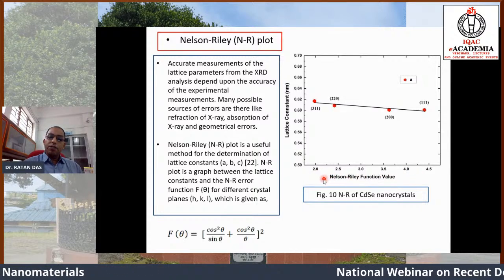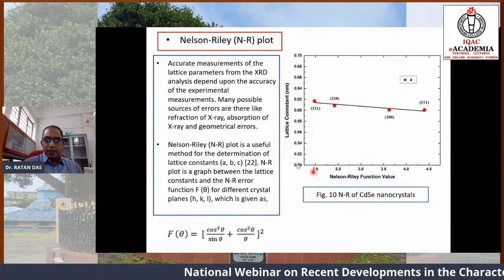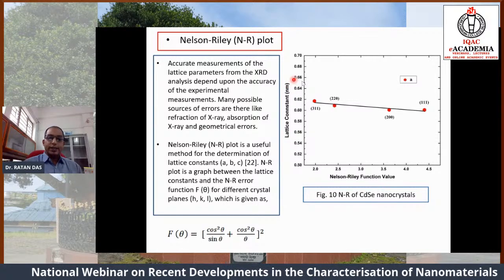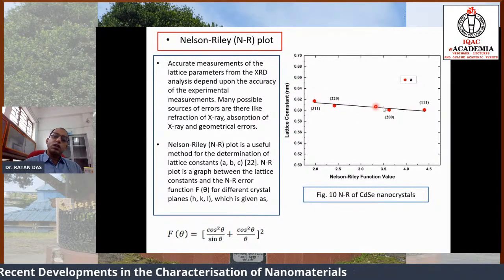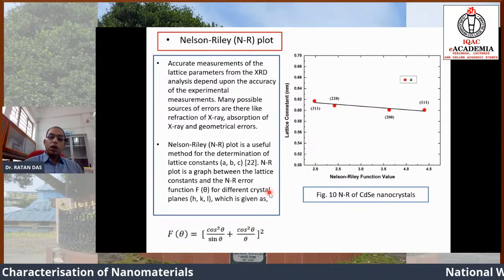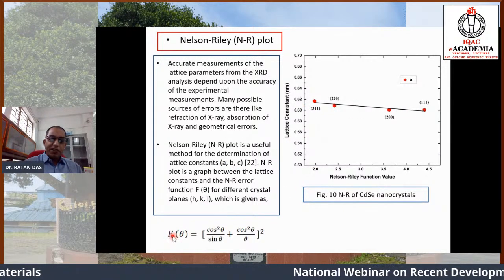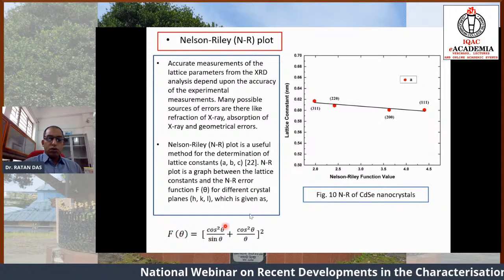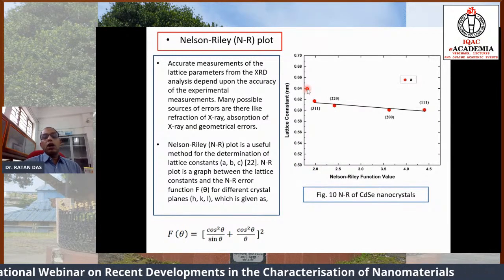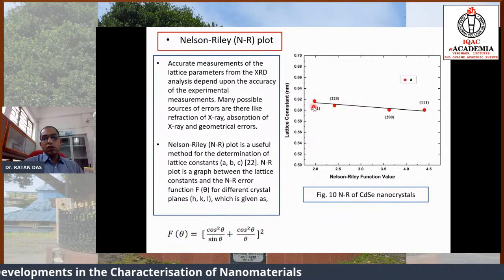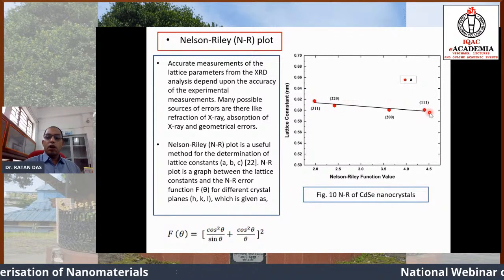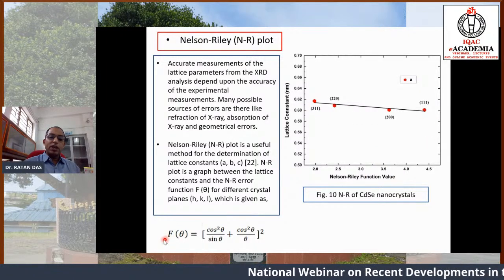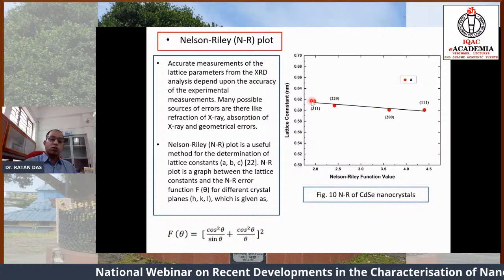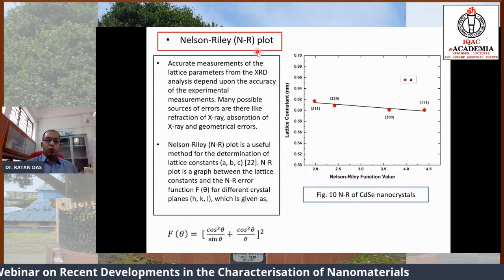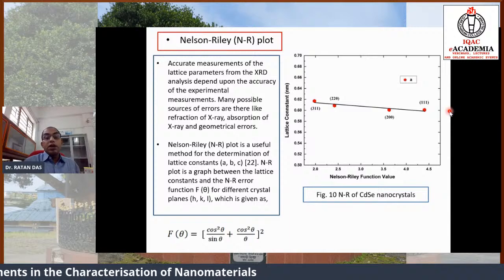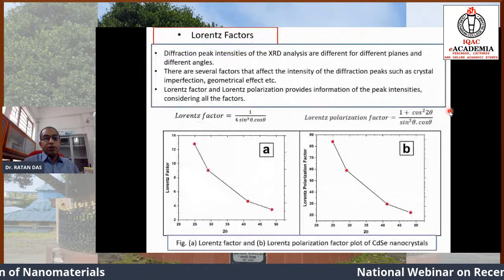We put the Nelson-Riley function value, f(theta), along the x-axis and the lattice constant value along the y-axis, and extrapolate the plot to the value where f(theta) tends to 0. So f(theta) tending to 0 gives us the errorless lattice constant value. You see, the lattice constant value is a bit higher and a bit lower on the higher angle side. But if we go for f(theta) tends to 0, it gives us the errorless lattice constant value. So by the Nelson-Riley plot method, we can obtain the lattice constant value from the X-ray diffraction pattern.